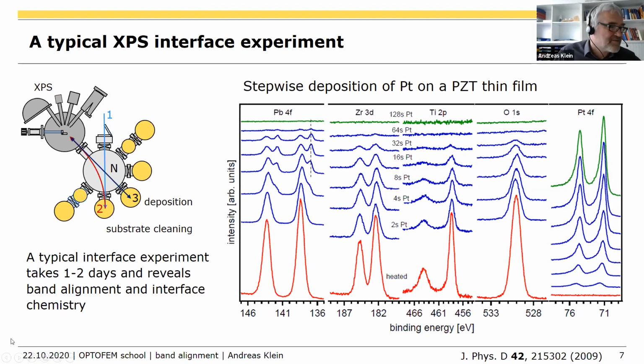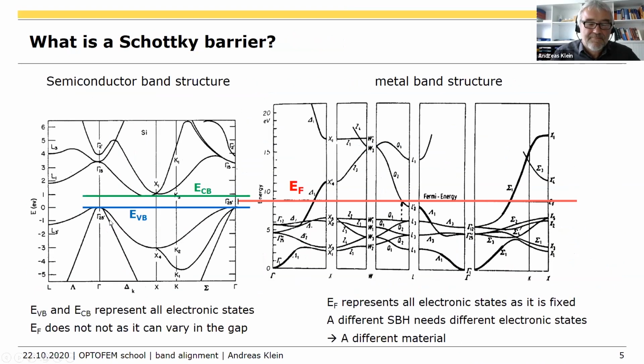Now the question from Pep. Band alignments are determined in the dark. Not necessarily. We can illuminate our samples. And as I said at the beginning, what is the Schottky barrier? Illumination will cause some carriers in a concentration which is too low to affect the band structure. So it will not affect the band alignment, I would say, and it will not affect Schottky barriers. What may happen is that if you have a material with defects, let's say zinc oxide, and you illuminate the sample, you form electron-hole pairs, and the electrons can be trapped in the oxygen vacancies.